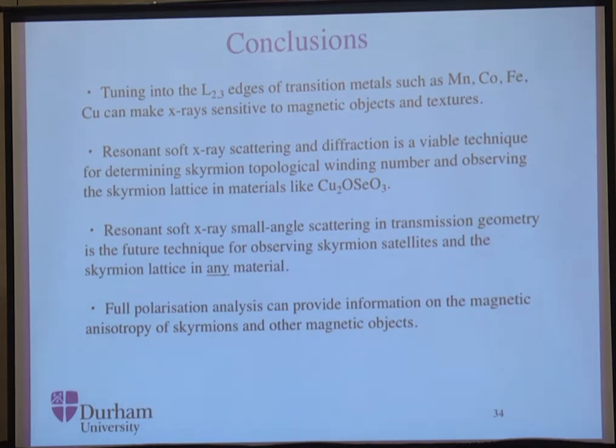Right. So we're looking at the origin in reciprocal space, and the little Skyrmion satellites or helical satellites would be close to the origin. Instead, we're looking right up around the 100 Bragg peak with really long wavelength X-rays. And the satellites, whether they be helical or conical or Skyrmion, are very close to the 100. And that means our wave vector is something like 0.010.